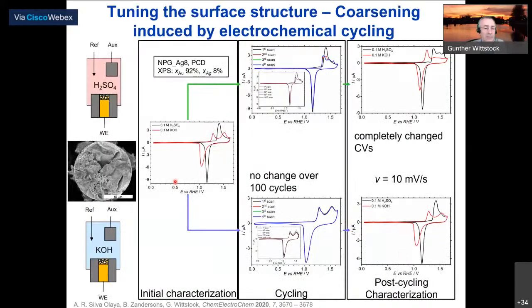And we can make cyclic voltammograms with it. And you see here the very nice cyclic voltammograms of these layers, with very high resolution. And then we observe very interesting changes. In the upper branch, you see cyclic voltammograms which we record in sulfuric acid, and in the lower one, which we record in potassium hydroxide solution. If we make the first scan, the appearance of the surface gold oxide completely changes. This big peak is lost, and instead these smaller peaks develop, which correspond to single facets of the gold crystal. And after even more cycles, that remains like it is.